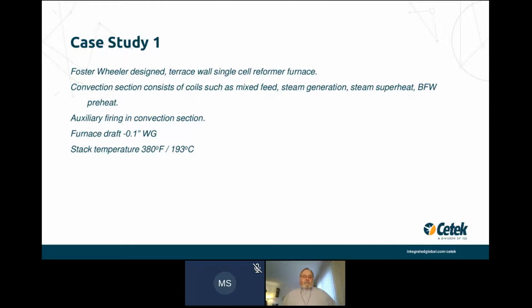So, a couple of case studies here. This first case study is for a Foster Wheeler designed terrace wall, single cell reformer. The convection section consisted of mixed feed, steam generation, steam superheat, and BFW, boiler feed water preheat. There was actually auxiliary firing in the convection section in this unit. Furnace draft was okay. Stack temperature was quite good.